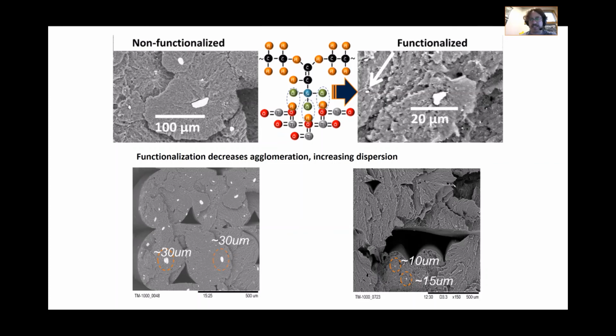PLA is a polyester, ABS is a copolymer triblock, so different types of polymers, and you use different functionalization agents for a polyester versus a copolymer. Non-functionalized, we see big agglomerates; functionalized, we still have agglomerates but they're much smaller. We did a size distribution: roughly 30 microns for non-functionalized agglomerates, and about 10 microns for functionalized, so about half to a third the size.